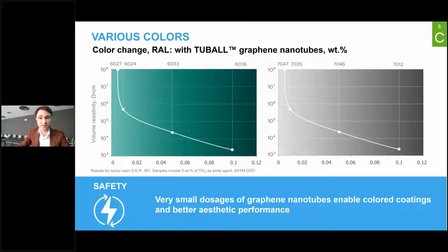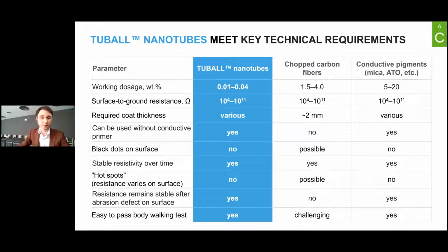Due to the low working dosage of graphene nanotubes, it will be possible to produce colored coatings. And in these two charts, you can see the dependence of volume resistivity and surface to ground resistivity on the working dosage of TUBALL, and at the same time the dependence of color in terms of RAL shades. So just an addition of a tiny amount of titanium dioxide or some other pigments can bring you light colors, and at the same time give you the ability to produce static dissipative or even conductive formulations. And let's compare single-wall carbon nanotubes with conventional electrically conductive fillers available on the market.